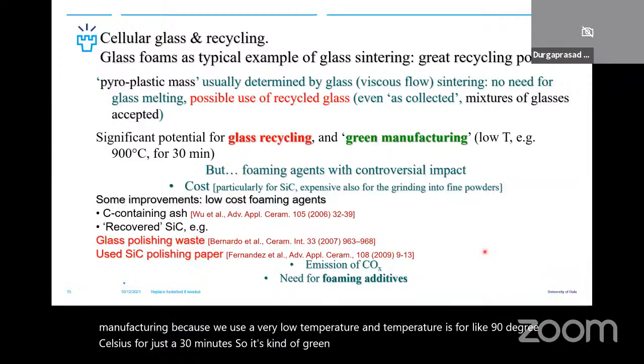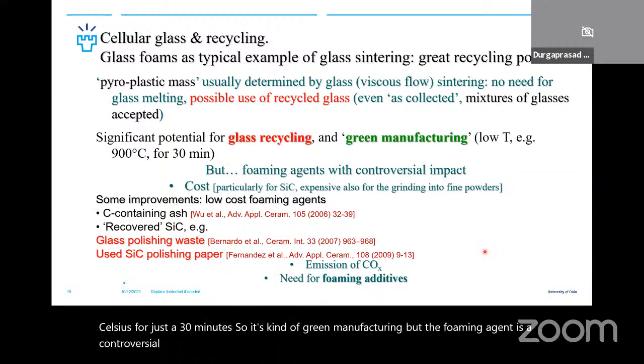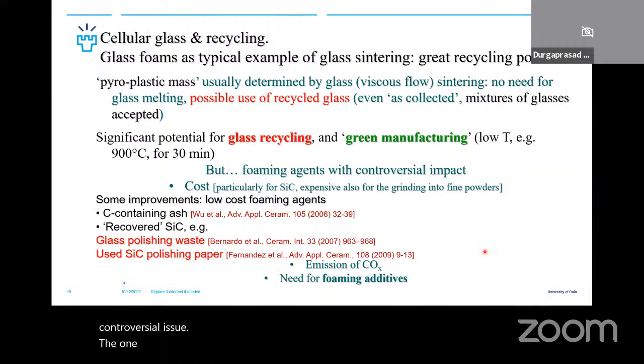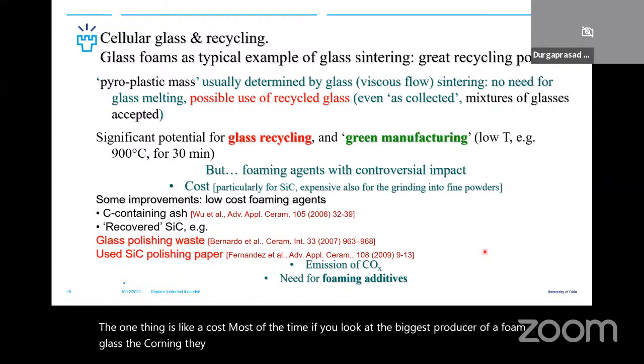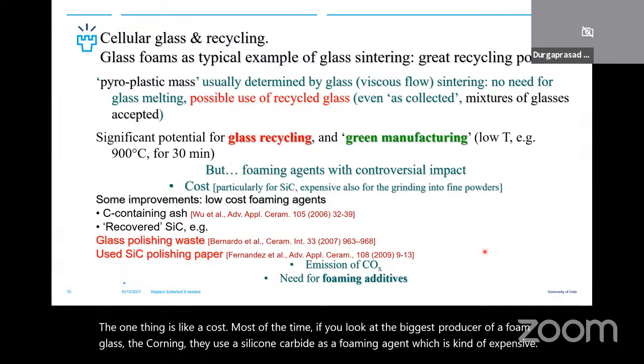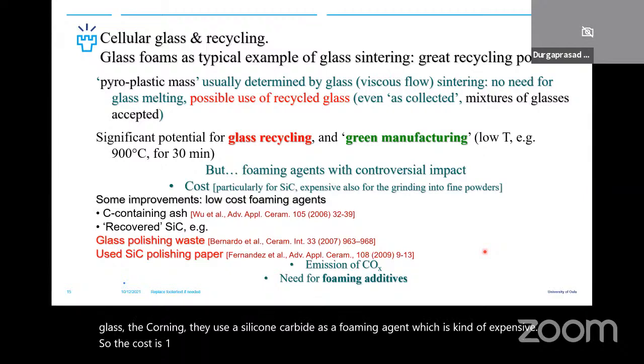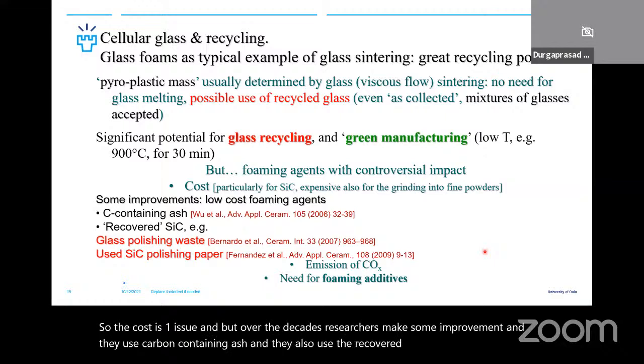But the foaming agent is a controversial issue. One thing is cost, most of the time. If you look at the biggest producer of foam glass, Corning, they use silicon carbide as a foaming agent, which is kind of expensive. So cost is one issue. But over the decades, researchers have made some improvements, and they use carbon containing ash, and they also use recovered silicon carbide, for example.